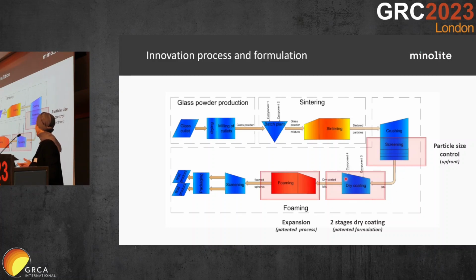After that, we have this patented step, which is two-stage dry coating. This is completely dry coating, no water, no binder, no adhesive. And then after that, we start with the expansion process. This expansion process is also patented. And then after that, we are screening the final product.